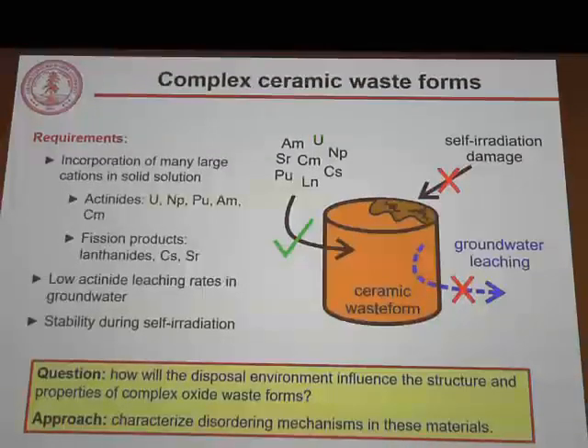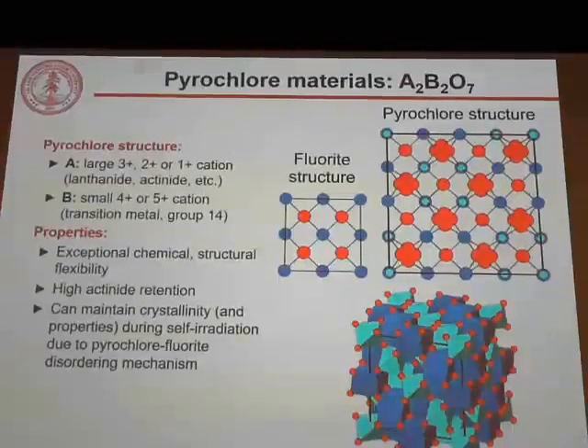And the approach here, because these are very complex materials with complex compositions, and therefore complex structures, is to characterize the specific disordering mechanisms they undergo at the atomic scale in these extreme environments. So I'll be focusing mainly here on one waste form type, the pyrochlore materials, which are A2B2O7 materials. And these are nice as waste forms because they can incorporate a lot of different cations. On the A site, you can fit large tri-, di-, or monovalent cations. So these include things like lanthanides and actinides. Whereas on the B site, you can fit smaller tetravalent or pentavalent cations, so things like transition metal fission products.